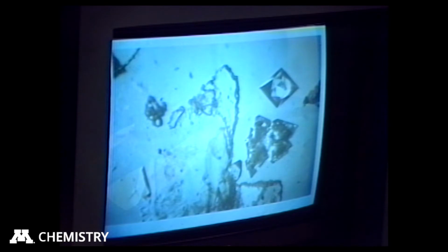The crystals are right and left-handed. And we call this conglomerate formation, when you have right and left-handed crystals independently. And here's another little one right here. The crystals, interestingly, are tetragonal. They have that same property that John's tetragonal crystal had. They have 4-fold symmetry in them. So here's a very unusual case where you can do a spontaneous resolution on conformationally interconverting enantiomers and completely stabilize that enantiomer in that form.